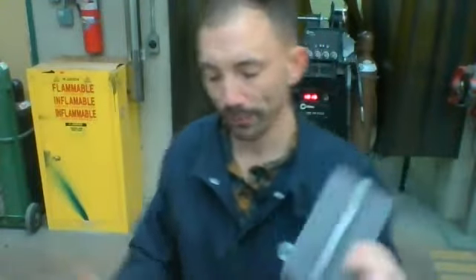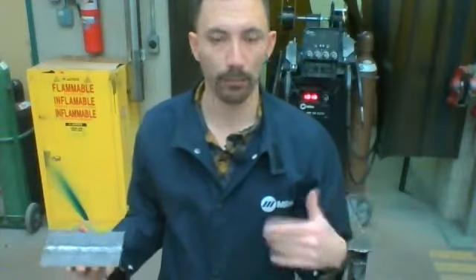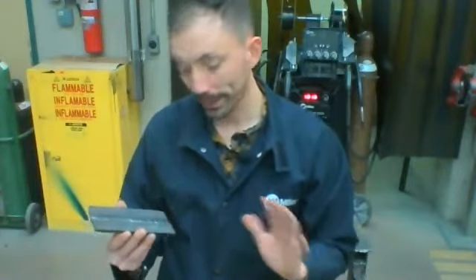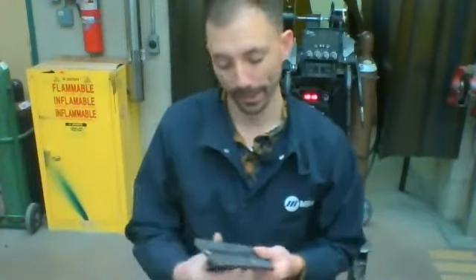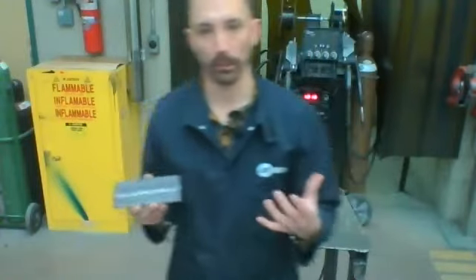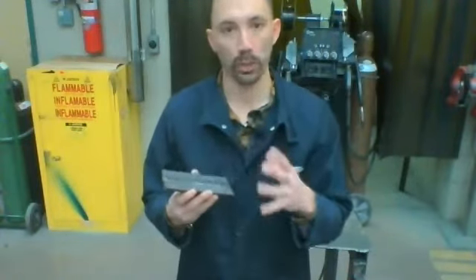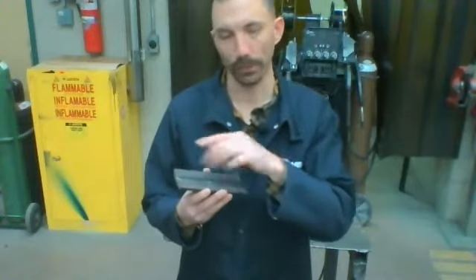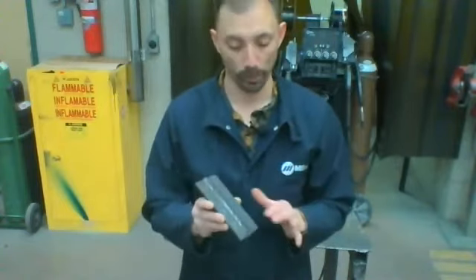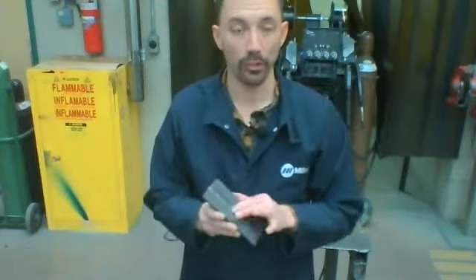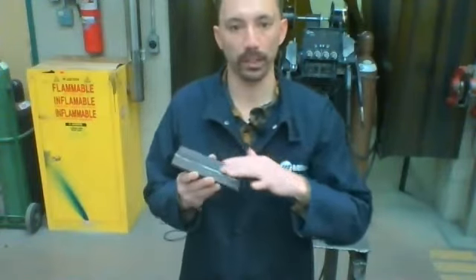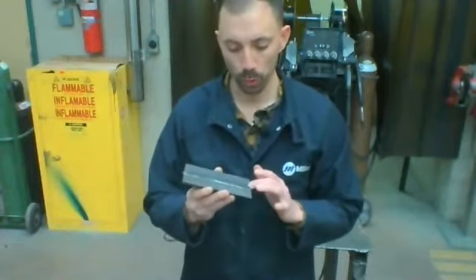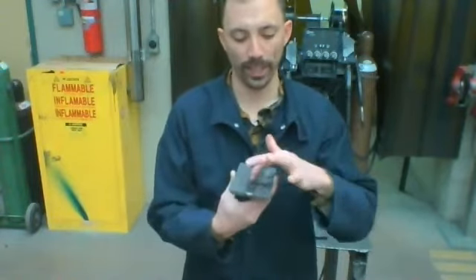So that's cool. I mean, that's pretty much a standard for welding pipe. If you're doing pipe in the flat position, you want to weave the caps, but it does have its benefits and its negatives. And one of the big negatives with this is when you're controlling such a big puddle and you got so much heat, because you're taking that liquid puddle and you're warming this whole thing with it. So when you do a cap, these get quite warm. The problem with that is you've put a lot of metal in one pass. When that cools down, that steel shrinks, and that's when that slag cap pops off, right?